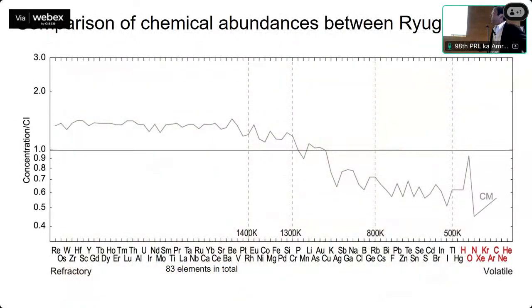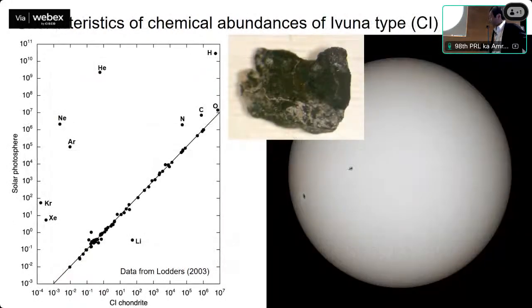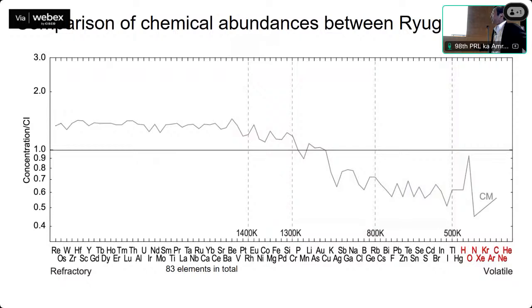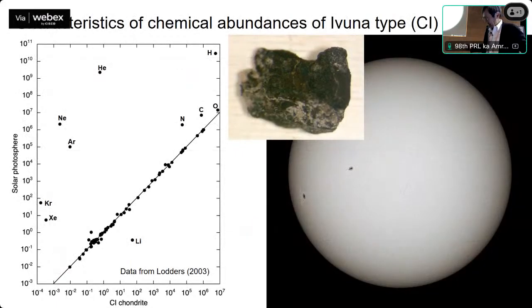So we measure chemical composition. In nature, there are 83 elements in total. On this side are the refractory elements, and on this side the volatile elements. The most volatile element is helium. And the vertical axis is the concentration, normalized to CI chondrite. Why normalize to CI chondrite? Because the composition of CI chondrite is similar to the Sun's atmosphere. Therefore, we believe CI chondrite has the average concentration of the solar system.